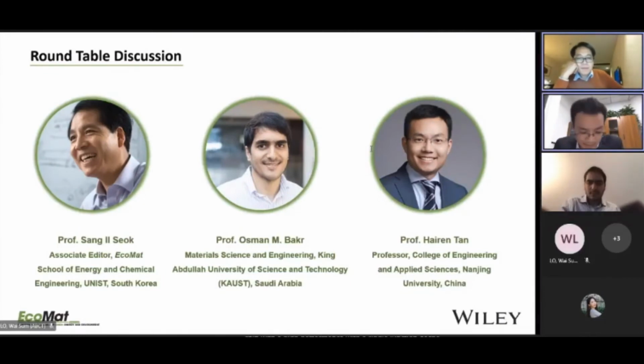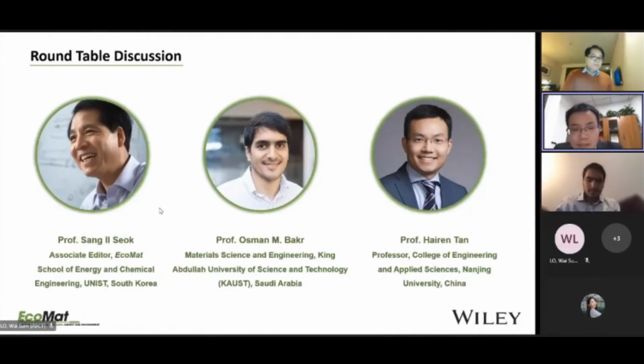Yeah. So thanks for your question, Professor Sok. I think that is a very interesting topic. Whether we can fabricate ideal bandgap perovskite single junction devices by using the mixed lead tin based perovskite, so that we should be able to further increase the efficiency of the single junction devices. If we only use lead, the lowest bandgap of lead-based perovskite is around 1.5. If we can lower it down to 1.34 or 1.35, I think that is the most ideal band gap for single junction devices.